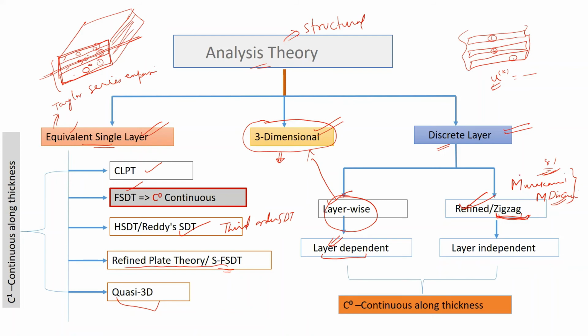We generally see that the displacement fields from the classical laminated plate theory and first order shear deformation theory give linear displacements across all the laminae. If we plot for this lamina, we get the displacement field as linear. So this is not the correct result. The variation would depend on the length to thickness ratio.